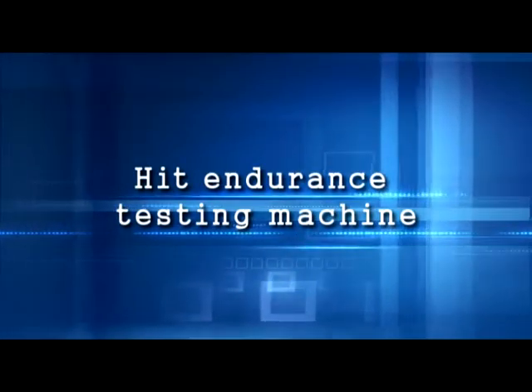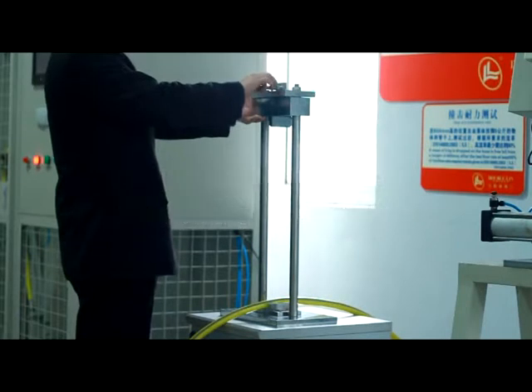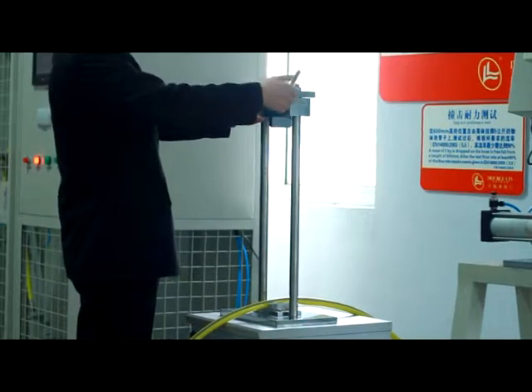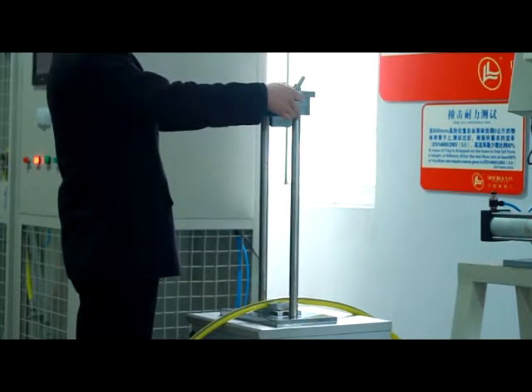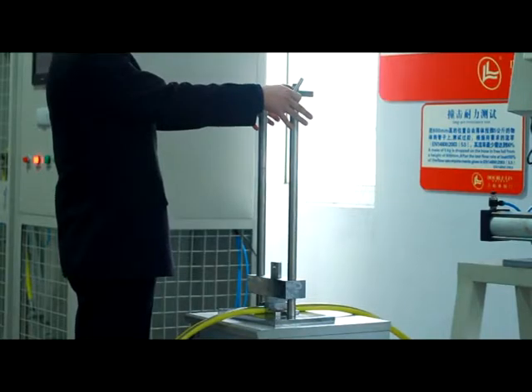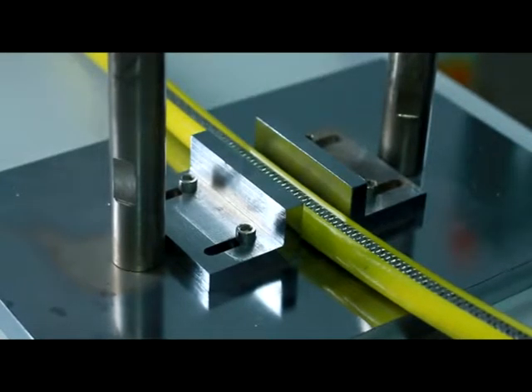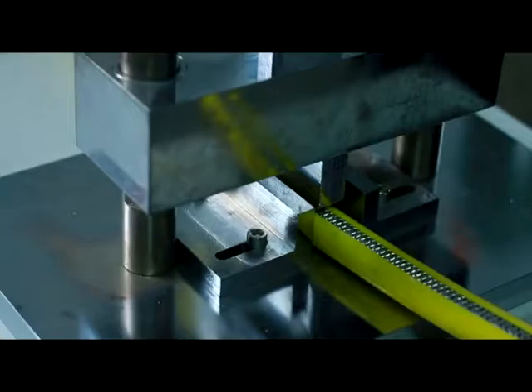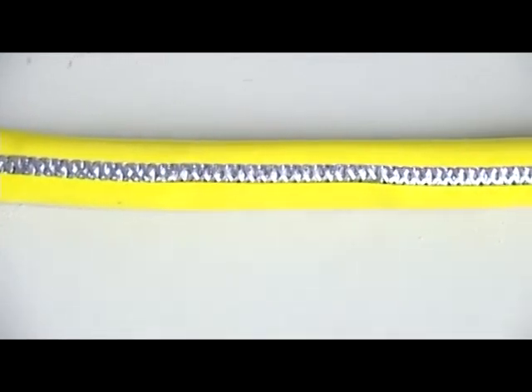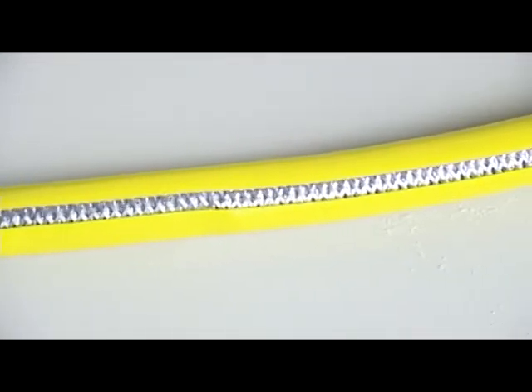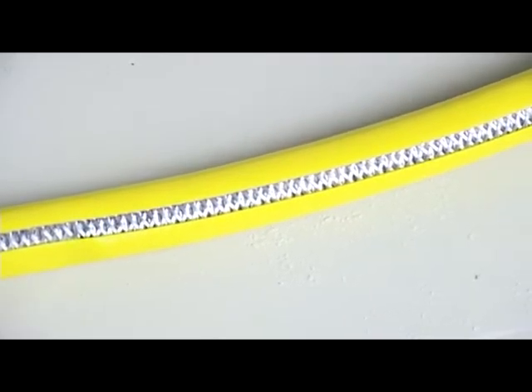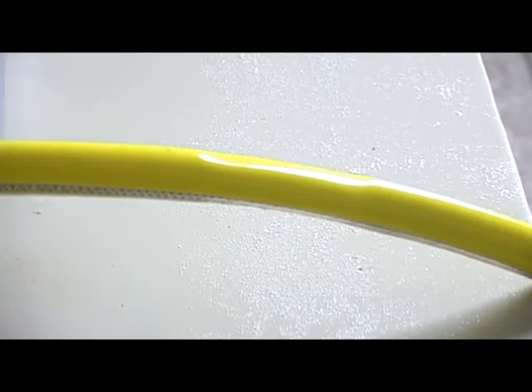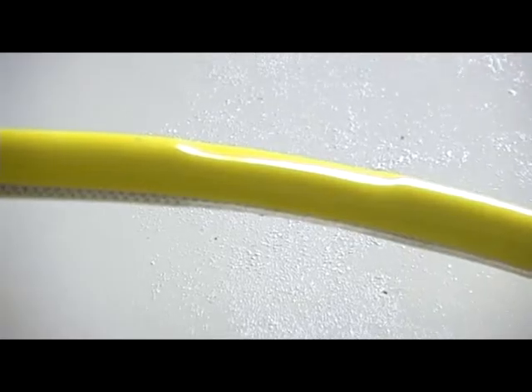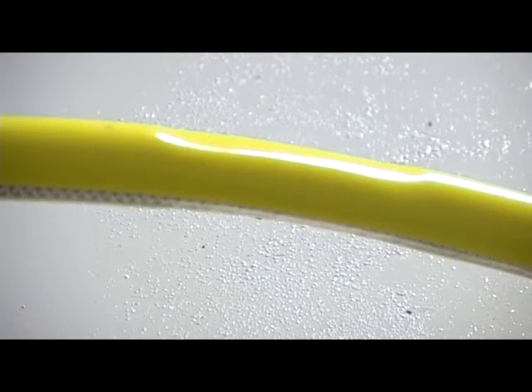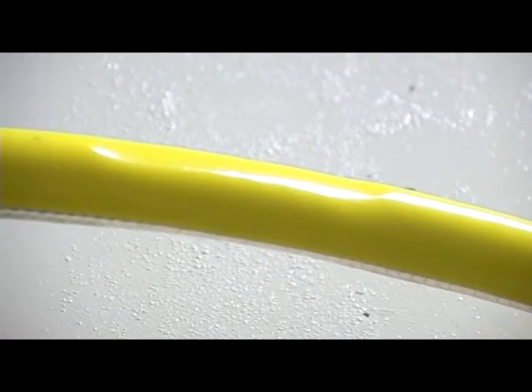Hit endurance testing machine test requirements. From a 2000 mm high position, freely throw a 5 kg object onto the tube. No damage happens after the test, according to the required flow terms of EN 14800:2009 3.5. The qualified flow rate may at least reach 90%.